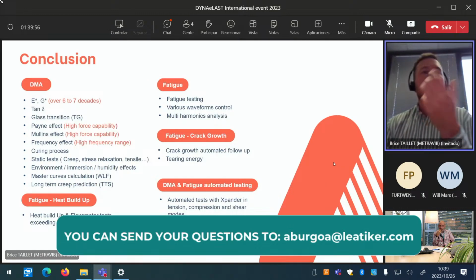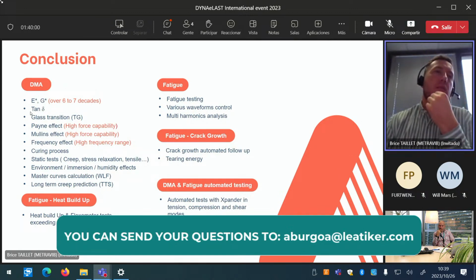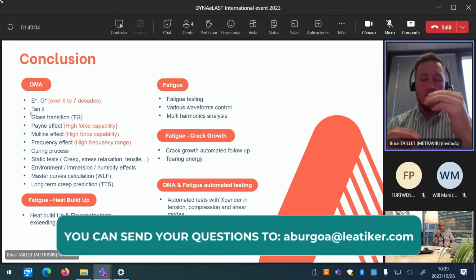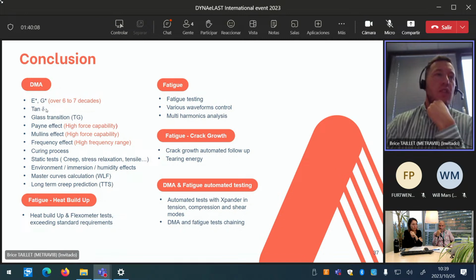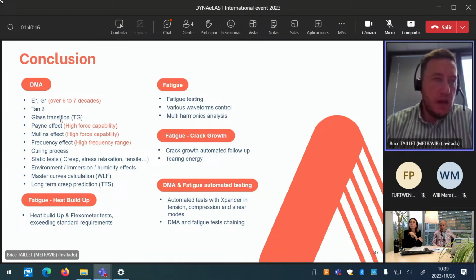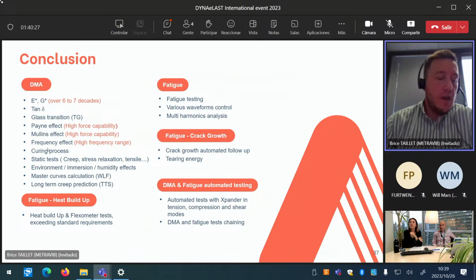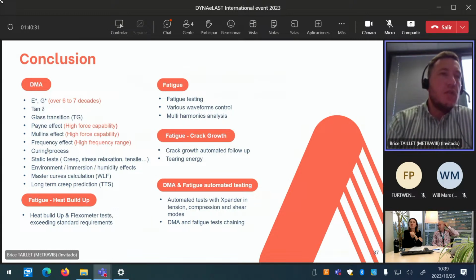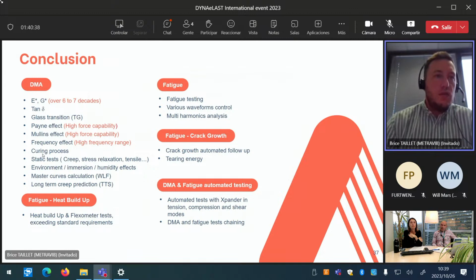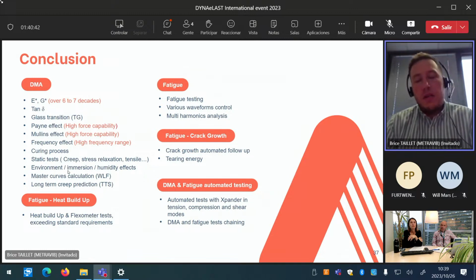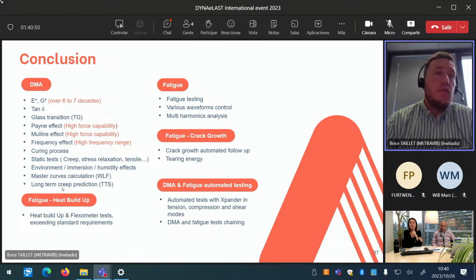Okay, as a conclusion, with DMA we can get the modulus E prime, E double prime, or G prime, G double prime, depending on the excitation mode we use. We're able to compute the tangent delta. Tangent delta is a unique factor to determine the damping properties. Glass transition is the main application for DMA, but we are also capable of getting the Payne and the Mullins effect, the frequency effect, and the curing process, because we are able to work on resin. I didn't show any case on this, but we can have some reticulation follow-up during a temperature stage, for instance. Static tests, we can use environment, we can control immersion and humidity, we can compute master curve, but in creep this time.